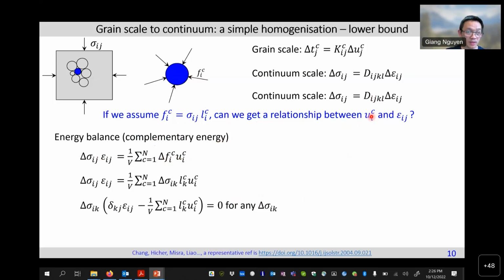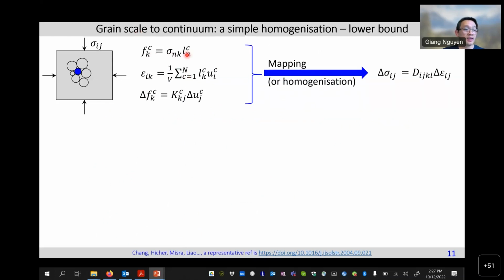If we use that, we can work out the relationship between the relative displacement between two grains and the macro strain. I skip all the details here just to make things faster, but the message here is the challenge. If we do substitution, we get the link between macro strain and relative displacement between grains, summed up as a volume average. So now we have the link between macro stress and contact force, and the macro strain and the relative displacement. We have the behavior of one contact in this case.